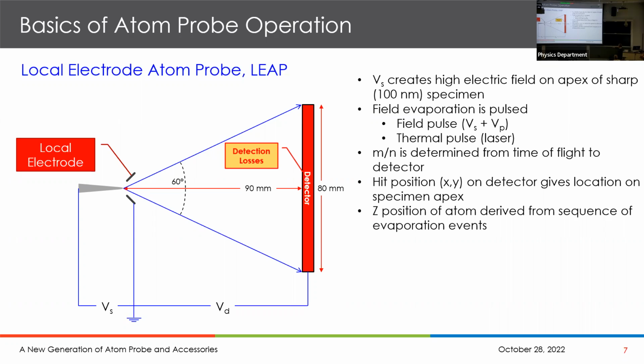But the atoms would fly through to a detector. Now, if this detector can record the XY hit position, then you can keep track of that and figure out how to reconstruct where those atoms must have been back on the specimen. And that's what that previous image showed. One thing to know is that today's detector technology gives us about 80% of the atoms. It's based on microchannel plates being the first line of detection, and they only get about 80% of the atoms. And so that's something I'm going to address, because what we would like to have in these images is 100% of the atoms.